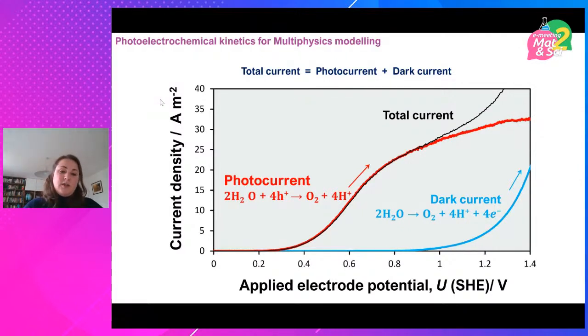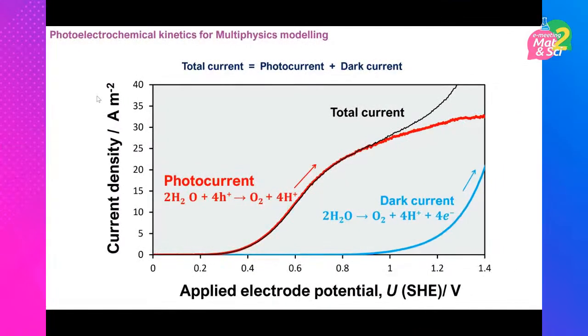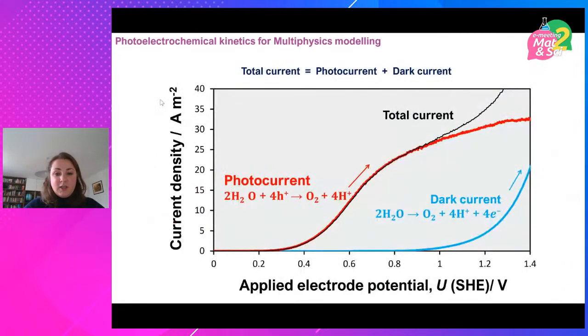And if you can achieve the same analogous process on, for example, the photocathode, then you will not need any external energy input at all, and solar energy will be sufficient. So the total current that you always measure will be a sum of the photocurrent and the dark current. And the idea is to model the kinetics such that you can see at which point the dark current becomes predominant, at which point you know that that's it. That's all you're going to get out of the system in terms of free energy.